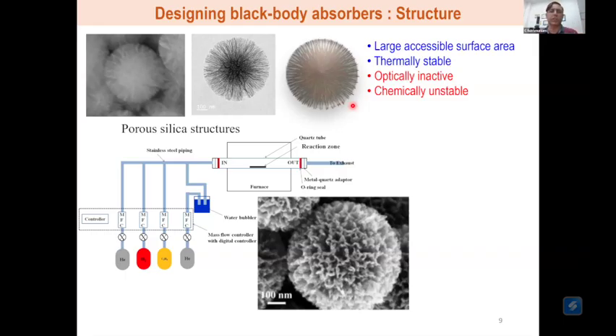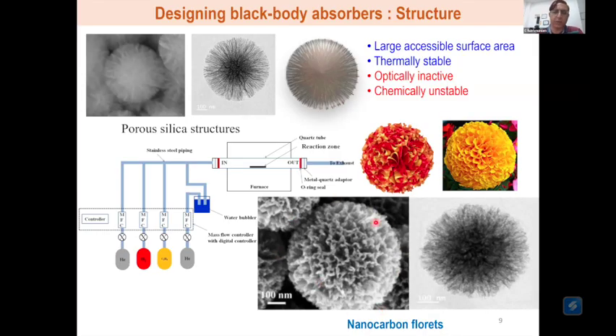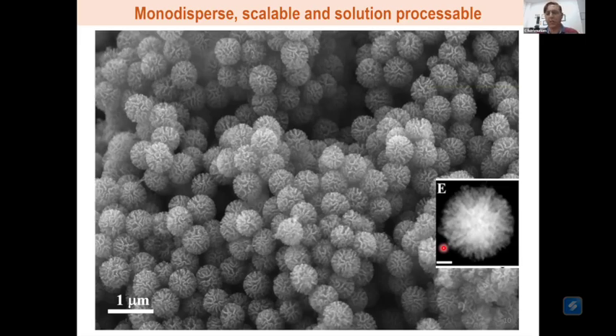So you use this silica as a template, and what you get is a complete, faithful reproduction of the template, but this time it's entirely made up of carbon. When we initially formed these structures, we thought it looked like something like a marigold flower. So we decided to call them nanocarbon florets. If you see the electron microscope image and compare it with this, it's an identical reproduction of the entire structure, except that every moiety of SiO2 here has been replaced by a carbon matrix here. So this is now an all carbon structure, which appears in the form of florets, and therefore we call it nanocarbon florets.